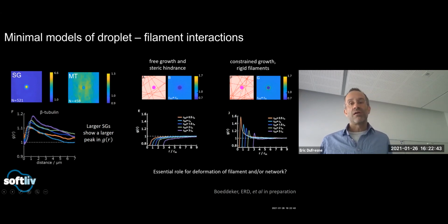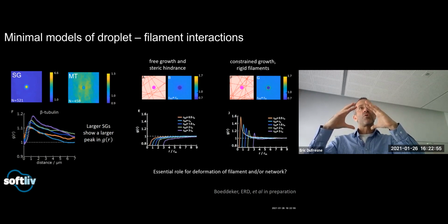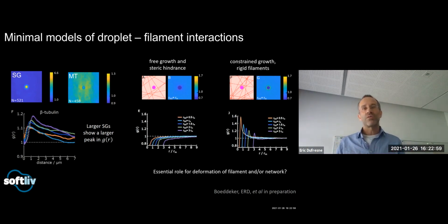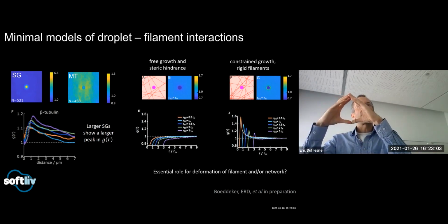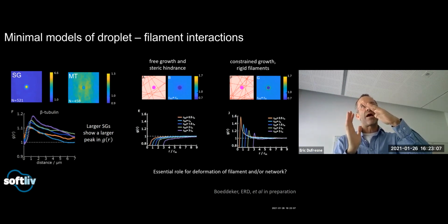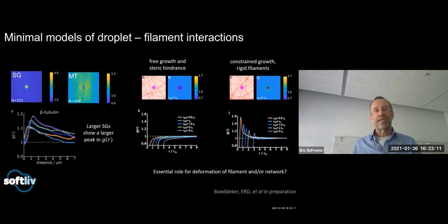Something that works a lot better, but not perfectly, is that if we pick a random location inside of our polymer network and start growing a droplet, and we keep letting the droplet grow until it runs out of room. In this model, the network is not deformable, but the center of mass of the droplet can move until eventually it finds a point where it has force balance, or 3 contacts basically, and it's isostatic and can't move anymore.